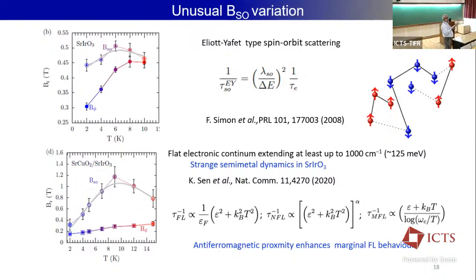Because I told you this is inversion symmetry. If there is a breaking, then you could go to the DP mechanism. There are two mechanisms, depending upon your system. Are there any other sources of temperature dependence, anything related to the phonons or the lattice? Is there any other relaxation mechanism beyond these two? Could be, but I don't know for this system.